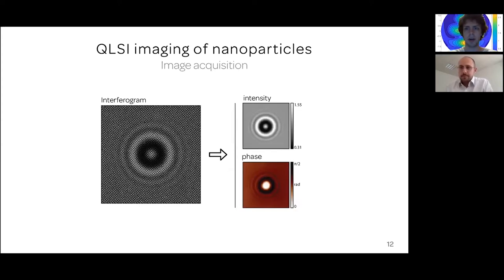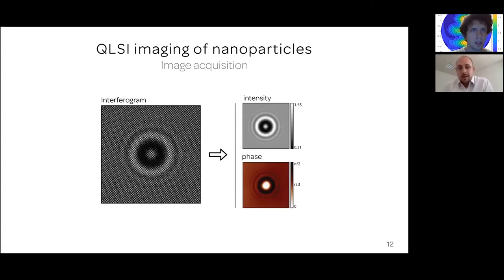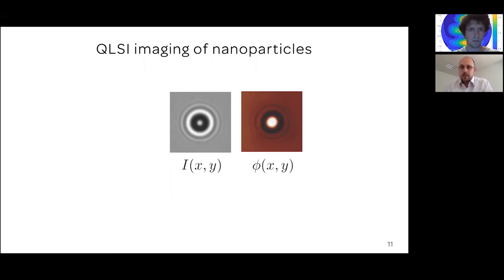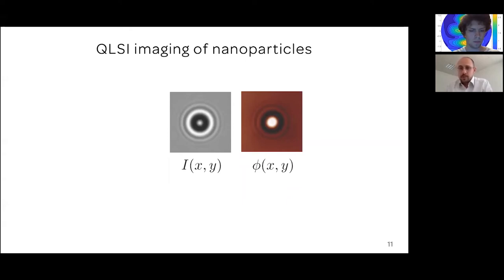A question from Dr. Ivan Sinov: does this technique require spatial and temporal coherence of the illumination? Actually, not really — you don't need a laser. This is one of the benefits of the technique. Although it is interferometric, you don't need a laser, and I would even say it's worse if you use a laser because of speckle and fringes. What you need is some spatial coherence, which you can achieve using colored illumination — a point source providing a plane wave — and this is enough to get these nice images.